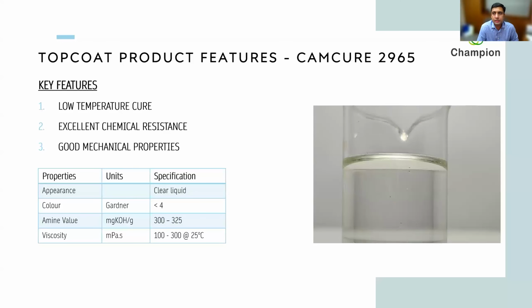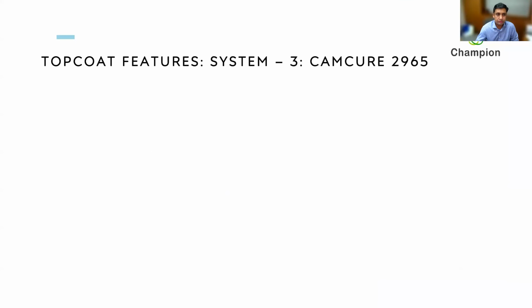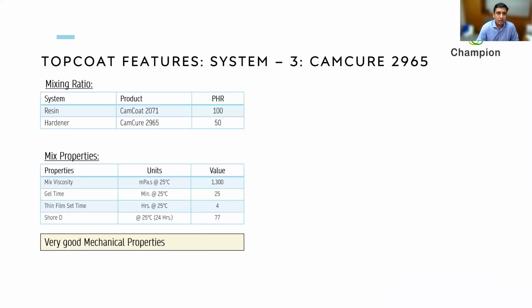Coming to the third system for the top coat, that's CamCure 2965. This system is very good for low temperature cures. It's also a very good system for chemical resistance. This system can be used in a very convenient mix ratio of 100 to 50 parts when it comes to basic liquid resin. You will notice here that the thin film set time is only 4 hours as compared to 7 hours for 2416.